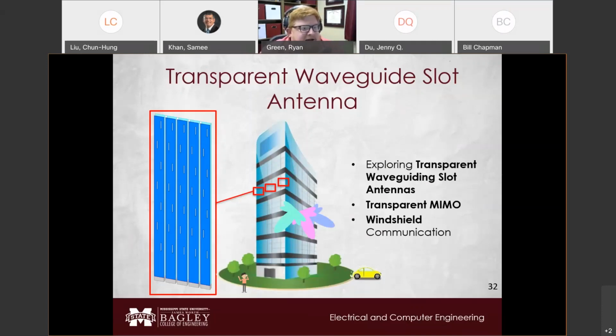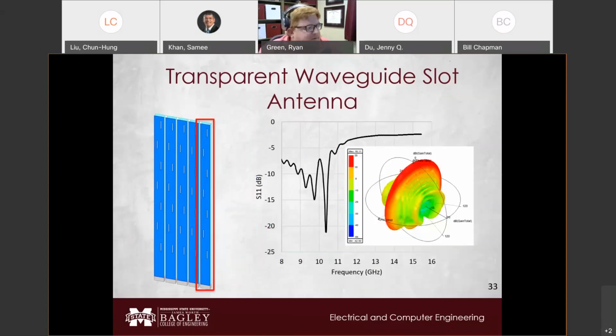Maybe instead of having an antenna that carries current and voltage on its surface and has this larger resistance, maybe if we had a wave that was being contained by a waveguide that could then be released, but that waveguide was optically transparent, maybe we'll have better results. And moving forward with that, there's some simulations that we performed, and ultimately with a 1.5 micrometer thick material and the same conductivity as what we see in our regular antennas at 10 gigahertz, or the antennas that we saw in the previous pages, we have a maximum gain here of about 18 dBi, which is outstanding if you really think about it.